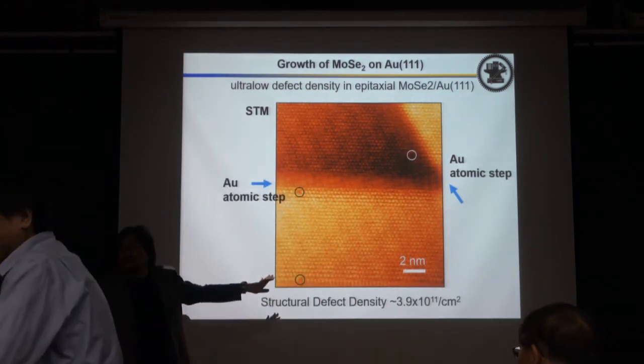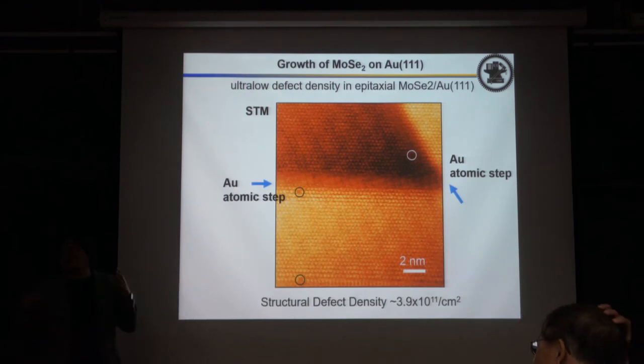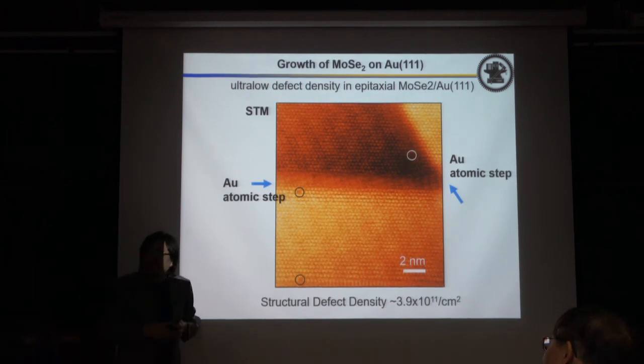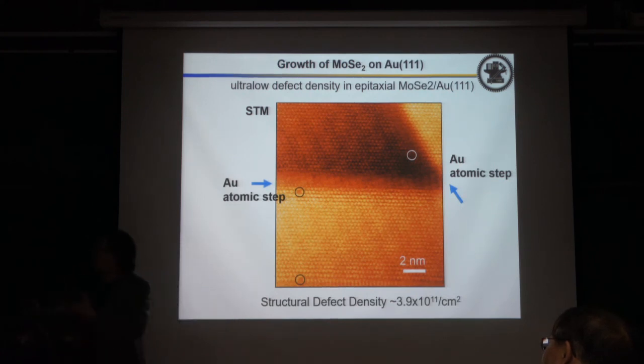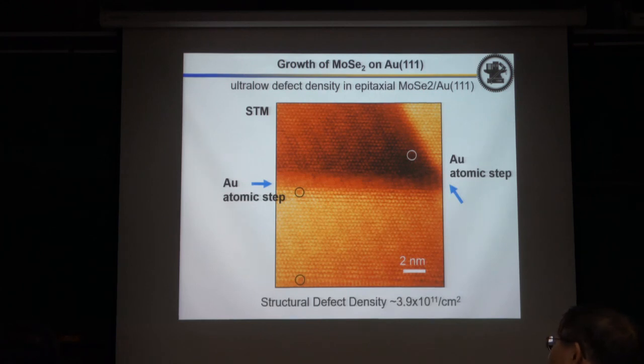Typically for band structure calculation, for example maybe on gold also, I think DFT can predict very precisely. But in the case of Moiré, with very large supercell and also with lattice mismatch, DFT actually has some limitation because we have to include too many atoms. So sometimes they have to use some technique to reduce the calculation, maybe some approximation or assumption. So that's the first principle.